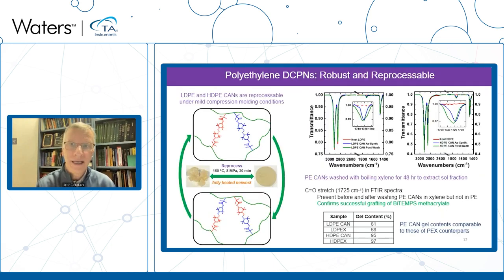remolding. The last case I want to illustrate is on this work that we just had published on Tuesday of this week, where we can take polyethylene, which is a linear polymer if it's high-density polyethylene, or it's a branched polymer if it's low-density polyethylene. And whether it's virgin material or it's waste material, we can actually do simple one-step reactive processing on this particular material and turn it into dynamic covalent polyethylene networks that exhibit robust properties associated with cross-linked polyethylene over a range of low temperatures. And then at high temperatures, we can reprocess the materials and actually recover those particular properties.